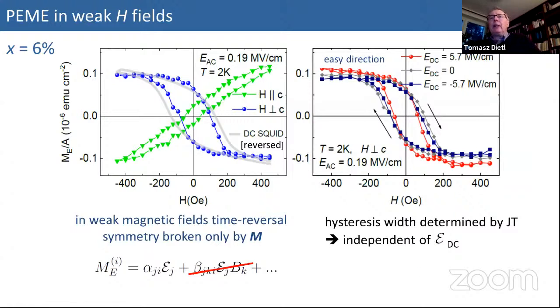And it is interesting that if we switch on, in addition to this AC electric field of relatively small magnitude, a large magnitude of DC electric fields, not too much happens, actually. We see that these curves look very similar, so there's not too much effect of the additional background electric field, which suggests that we have a linear dependence on electric field, and the derivative, which we measure by applying the AC electric field, is constant. So the effect is linear in electric field as expected from this formula.